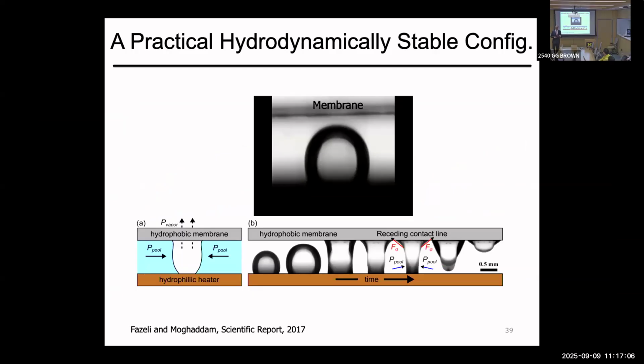I'm now convinced that this is a cool experiment, but I still believe I need more validation. So how about if I do this validation, where I put a hydrophobic membrane with a hydrophilic surface at the bottom, and then the bubble comes in, reaches the surface, and wants to dewet. The surface tension essentially grabs the bubble and takes it. That's why it goes from spherical to cylindrical. It means there's a significant force pulling the bubble from the surface and out.